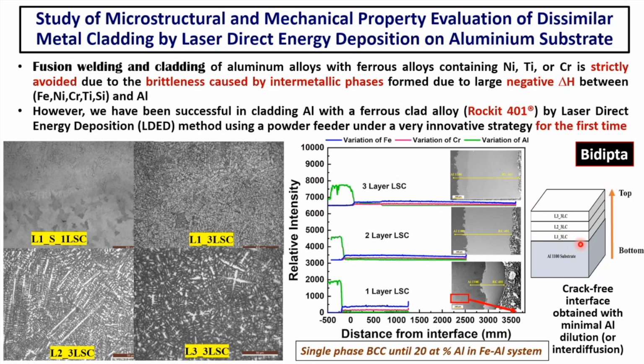And why this marginal melting is necessary is to ensure that the alloyed zone that you form in the interdiffusion intermixing zone has aluminum content less than 20 atomic percent. So that even if you melt and intermix iron with aluminium, the level of aluminium is less than 20 atomic percent, so that the brittle intermediate phases don't form. FeAl or Fe2Al starts forming only after the 20 atomic percent level.